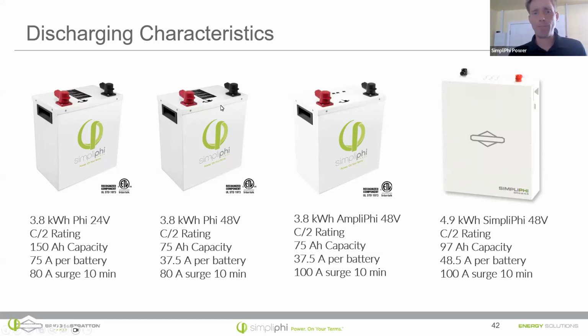out of the Phi battery, both varieties here, the 48 and the 24 volt, and that amperage is really limited on the 24 volt to that fuse and the BMS there. So again, 80 amps surge out of the Phi battery. You can get 100 amps out of the AmpliPHI battery. You can do that for up to 10 minutes.